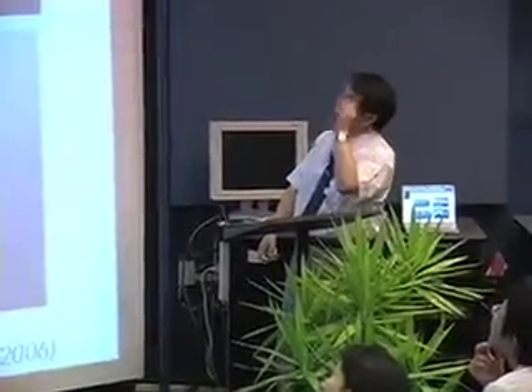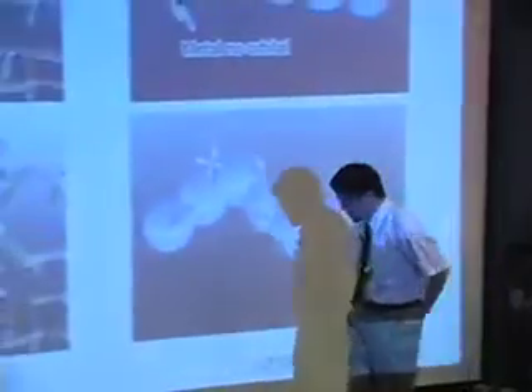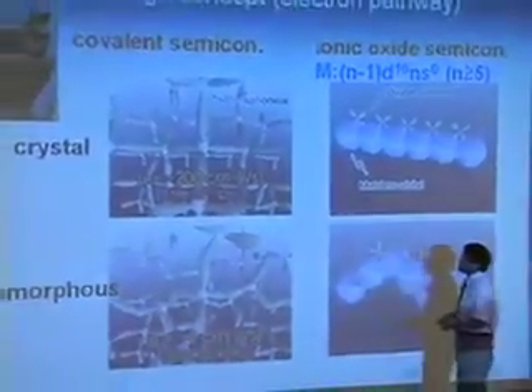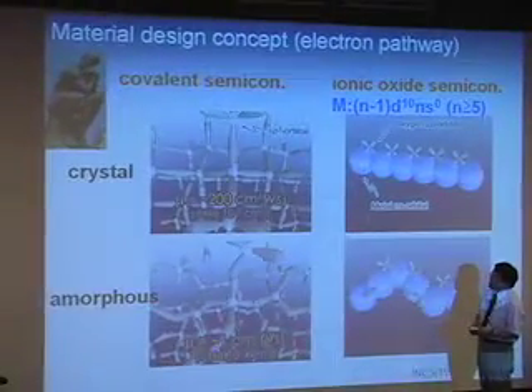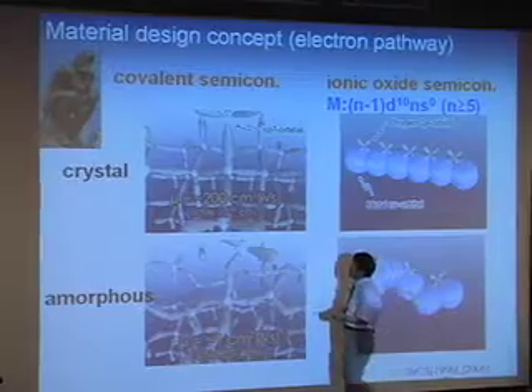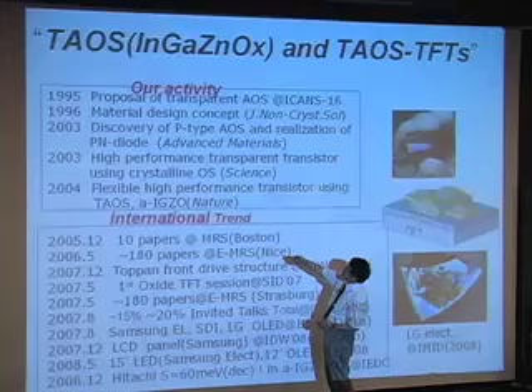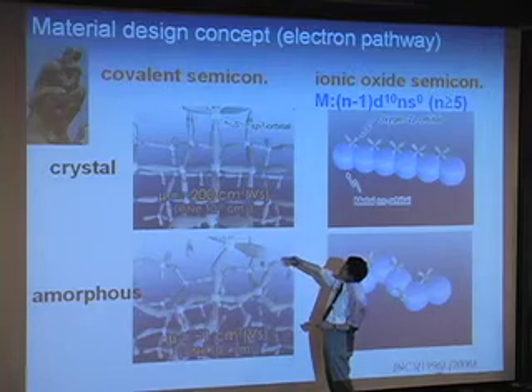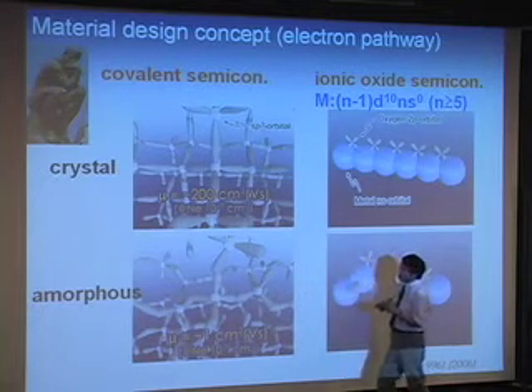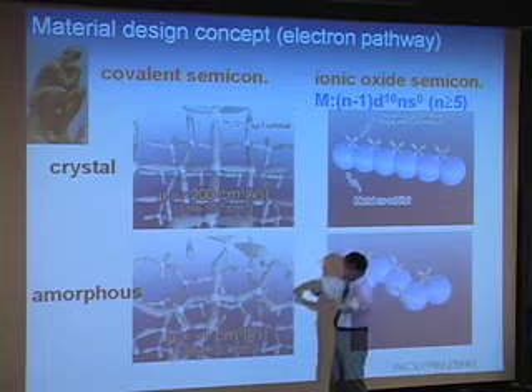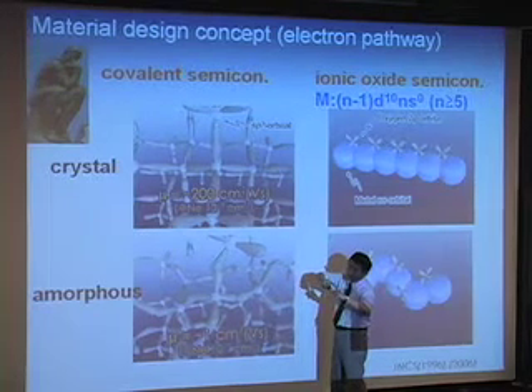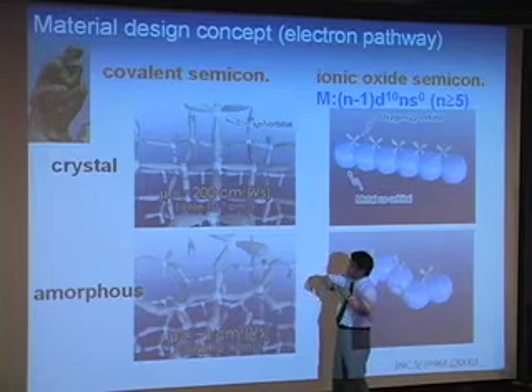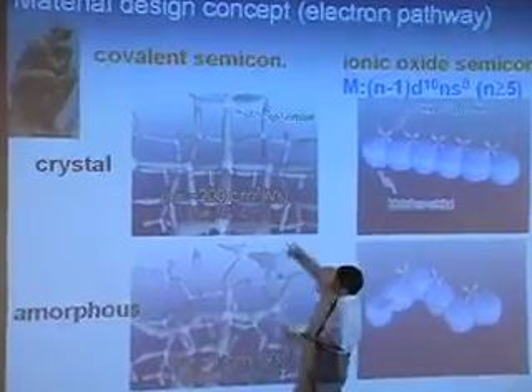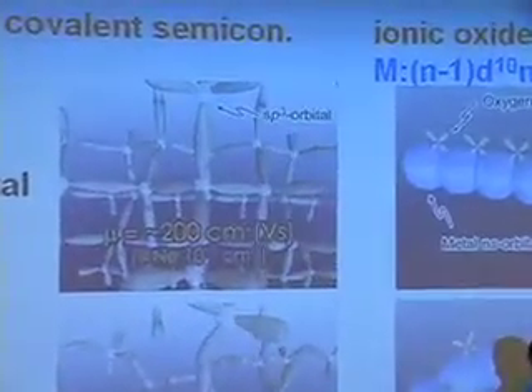This is my policy. Okay, this is a material design concept I proposed in 1996. This is the case of silicon. The electron mobility of silicon for n-type is 200. When silicon becomes amorphous, what happens? Silicon has sp3 chemical bonding, so the bond is rather directional. So when silicon becomes amorphous, the bond overlap between two sp3 orbitals is not so good. As a consequence, mobility is dropped by two orders of magnitude.